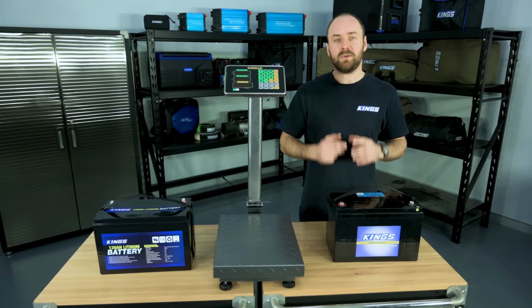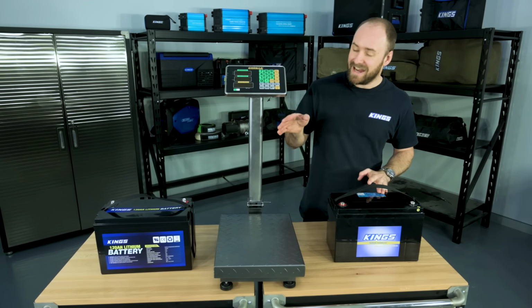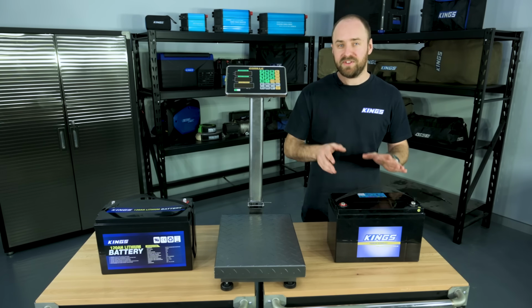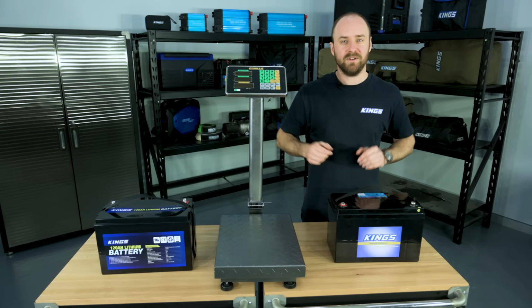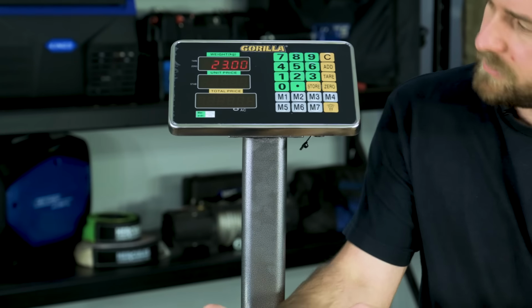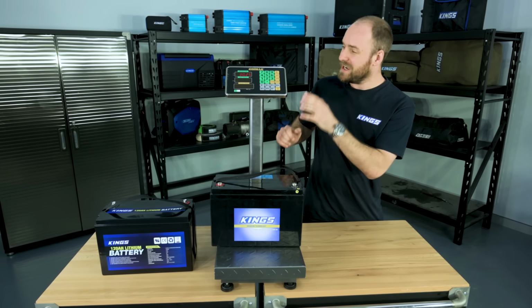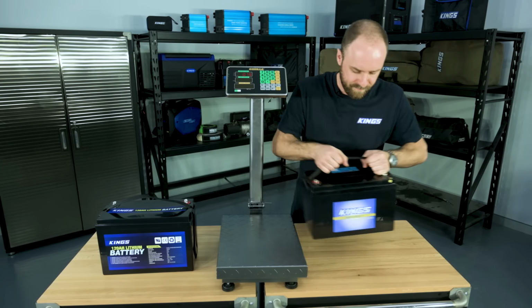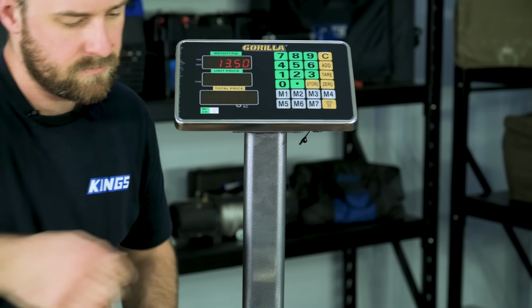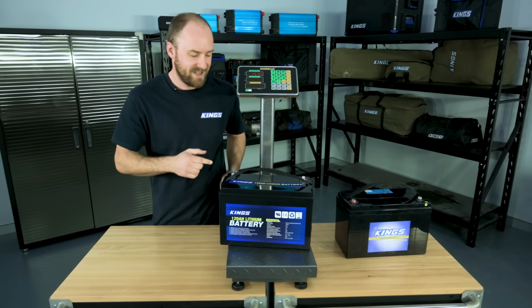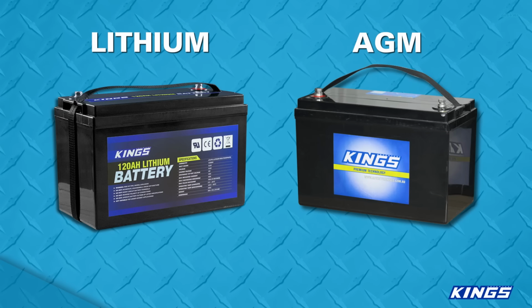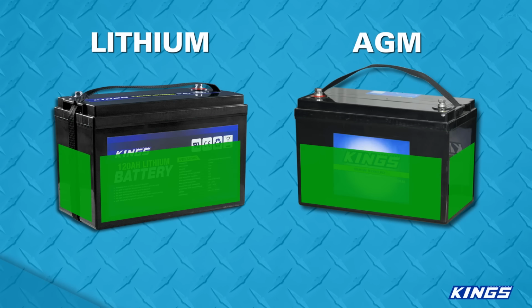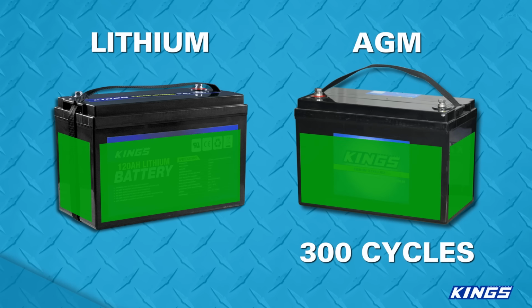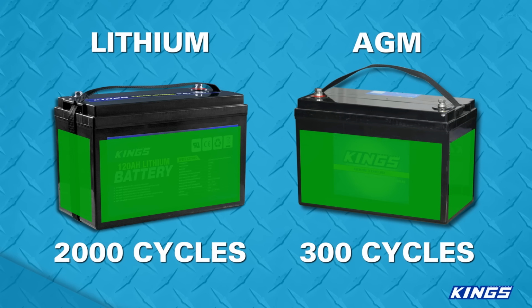First, let's do a really quick comparison of an AGM battery and a lithium iron phosphate battery of the same capacity. These are both 120 amp hours. The AGM battery is around 30 kilos, while the lithium is just 15. If you use both these batteries from 100% down to 0% repeatedly, you'd get about 300 cycles out of the AGM. But in those same conditions, you'd get 2,000 cycles out of the lithium ferrous phosphate.